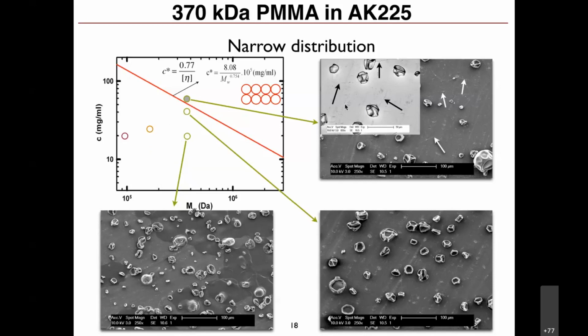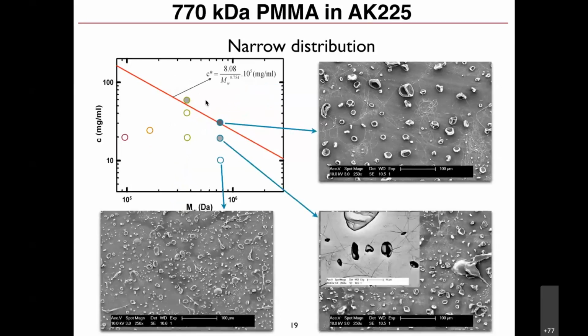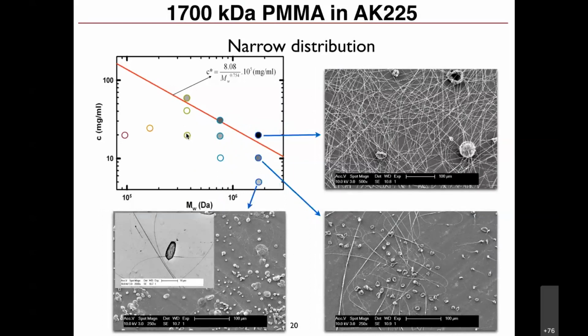So in theory, this theory is good. You go to higher molecular weight, you see that for the lowest concentration, we don't see any fibers. If you go slightly above, we start seeing fibers, even though we are below this line. And of course, if you go close to the line, you get a lot of fibers. And now the molecular weight is 770. That's double what we had seen previously. And if you increase it even higher, like 1700 kilodalton, then even for very low concentration, almost 5 milligram per milliliter, you already start seeing the fibers. And of course, if you go over the line, you see a huge amount of fibers there.